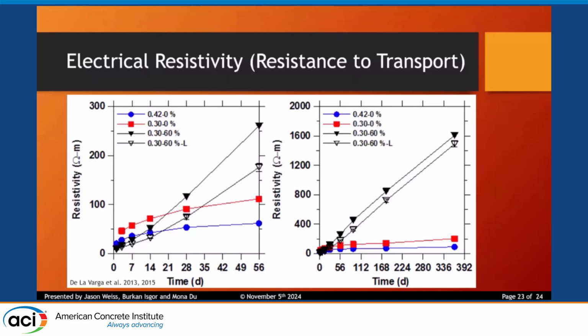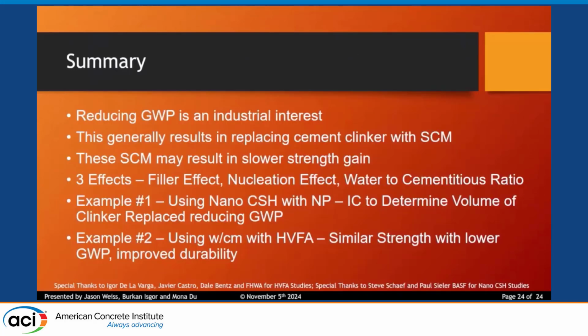So this big jump doesn't correlate necessarily with the amount of material that's reacting. It correlates with the fact that you've shifted the transport from the capillary pores, the big fat pores that everything wants to flow through, to the little tiny gel pores, and you now have a very long-lasting structure. So there's huge benefits in doing this. Substantial reduction in GWP, substantial reduction in the amount of clinker that's being used, but improvements in performance without problems with early age strength development.